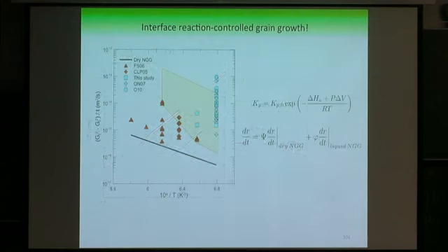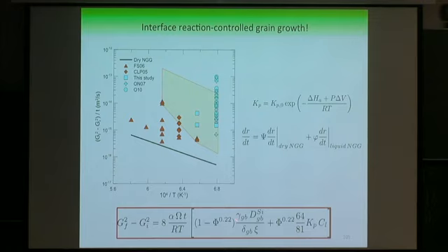So I've decided to take the grain sizes determined in my study and fit an empirical law, which here is termed Kp, which corresponds to the precipitation rate at the crystal-liquid interface. I re-implemented that in this kind of equation where we have contiguity and wetness, and get a final grain growth law where the grain size exponent is 2 and is dependent on diffusion of silica at grain boundaries, the effective grain boundary width, and also the precipitation constant that has this form here.